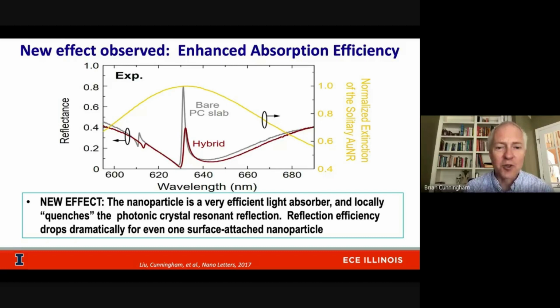One of the things that we observed that was very interesting is that if you have a photonic crystal that ordinarily would be a very efficient reflector, if you put absorbing gold nanoparticles on the photonic crystal, the reflection would go from highly efficient down to less efficient. We call this a new effect, but it really makes sense because the gold nanoparticle is robbing the photonic crystal of some of its resonant energy. And so rather than being an efficient resonant reflector, now the presence of the gold nanoparticle is absorbing energy, stealing it away, so the resonance is quenched partially.